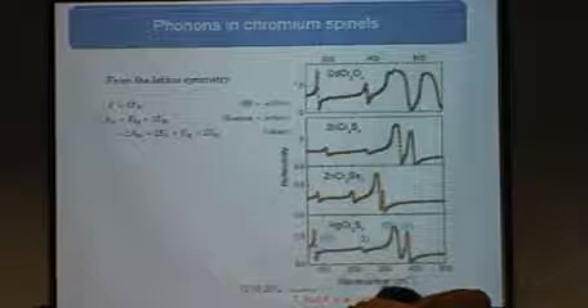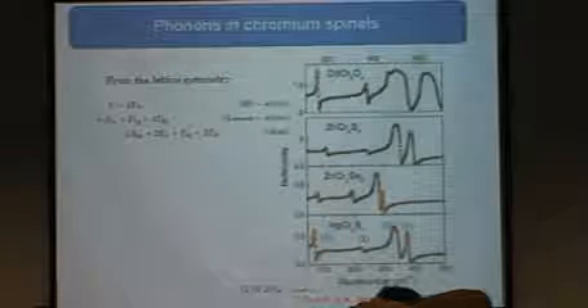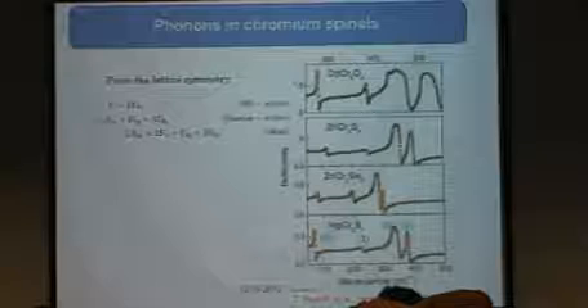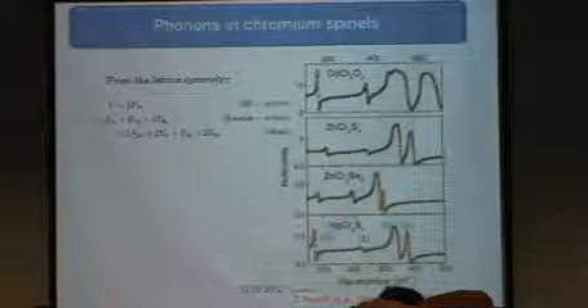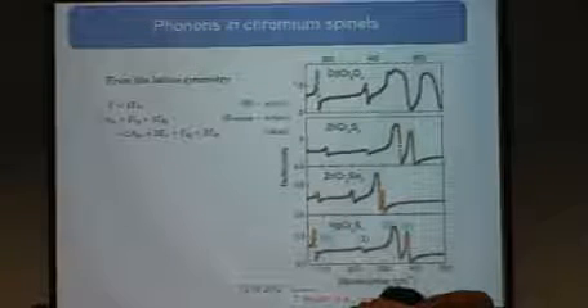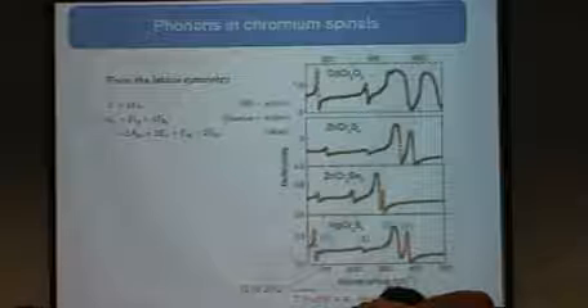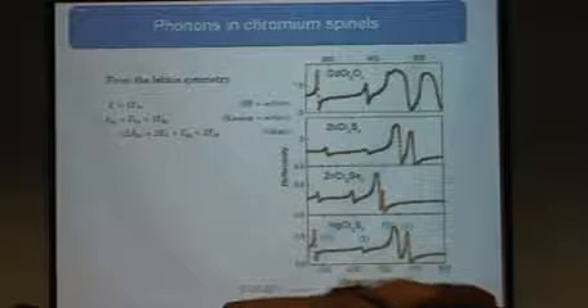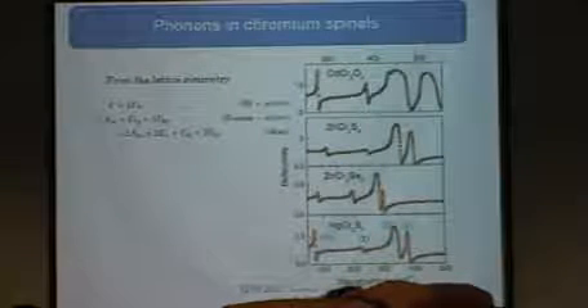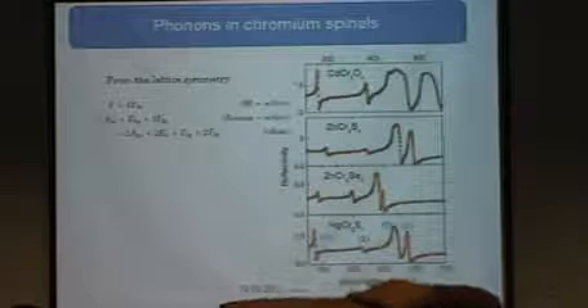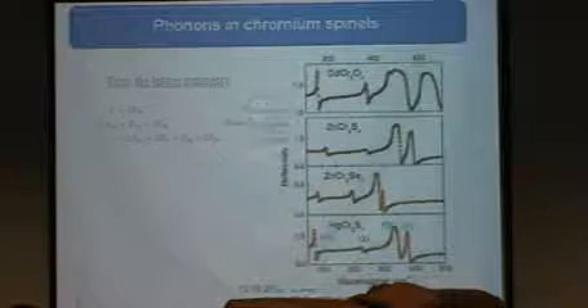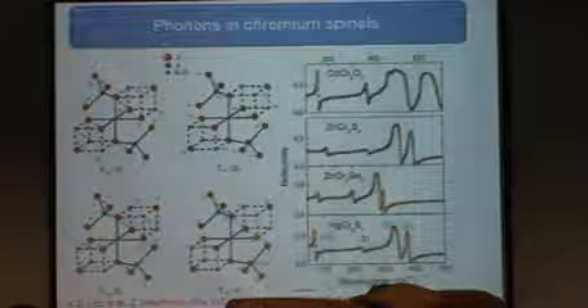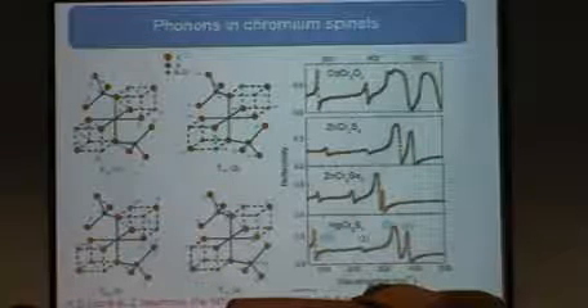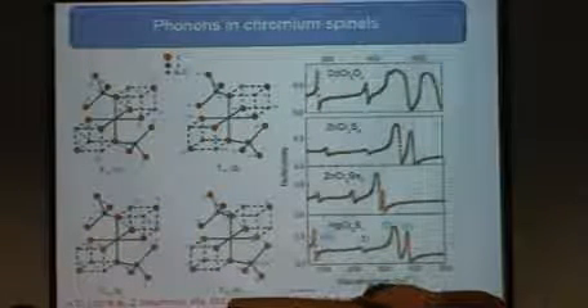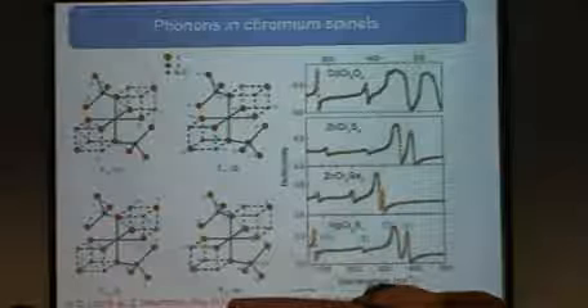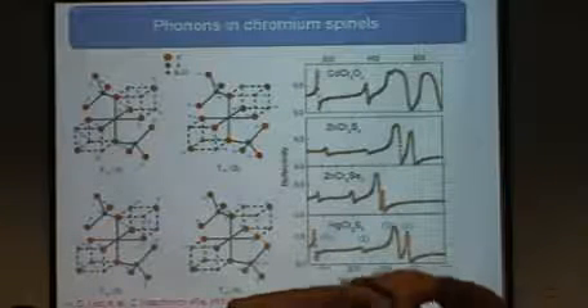Theoretically, from the lattice symmetry point of view, there are four infrared active phonon modes. Here is the experimental data of the chromium spinels. About the origin of these phonon modes, in the literature they say almost all the atoms contribute to each mode. The contribution of a few atoms can be less or more for different modes.